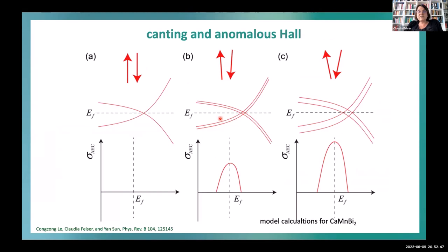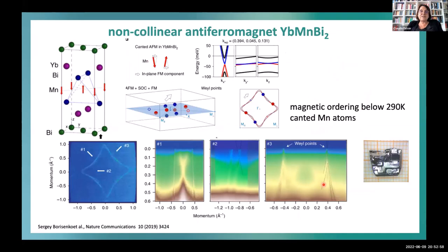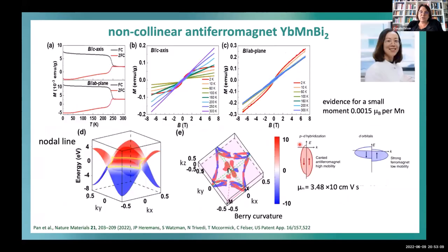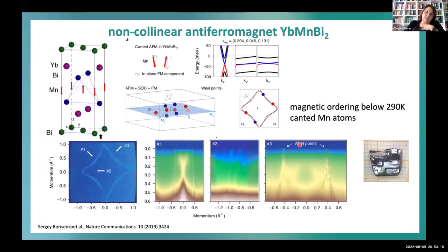non-canted behavior, and we can say simply if we induce canting in a material, we see really a large anomalous Hall conductivity, and then also an anomalous Nernst. Okay, at the end of the day, I can tell you, we used ytterbium manganese bismuth. This was also already seen as a Weyl semimetal some time ago, and in this paper from Borisenko, they already argued that the material is canted.